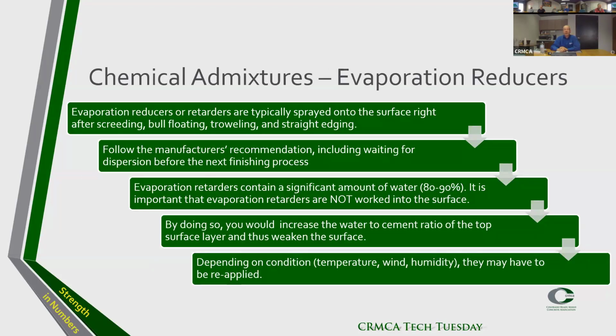Chemical admixtures, evaporation reducers. Evaporation reducers or retarders, they're typically sprayed on the surface right after screeding, bull floating, troweling, or straight edging. One thing that is highly recommended is to really follow the manufacturer's recommendations, waiting for dispersion before the next finishing process. These evaporation retarders generally contain a lot of water. So now, I just read one, Confilm, it says add 90% water to the concentrate that you get. So that means there's a lot of water getting on your surface, and please do not work that retarder into the surface.